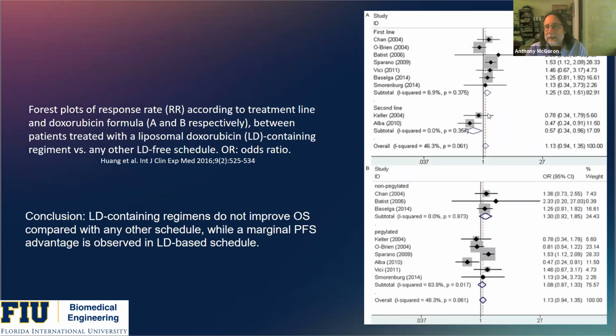Response rate, very similar if we look at the data across different studies for this response rate. So the conclusion here is that liposomal doxorubicin containing different chemo regimens do not improve overall survival compared with other schedules, while a marginal progression-free survival advantage is observed in these schedules. So this certainly doesn't mean that there's no advantage to liposomal doxorubicin.